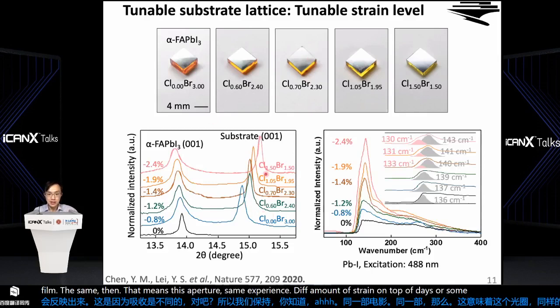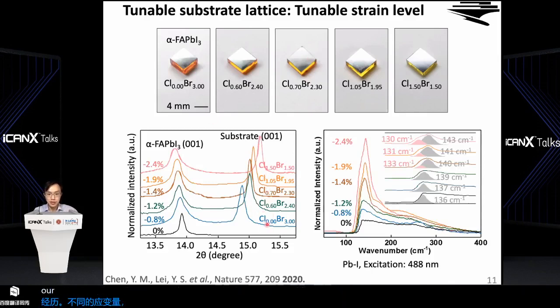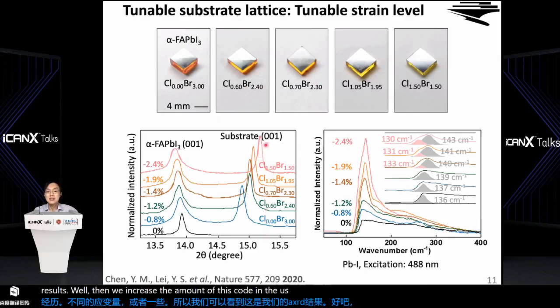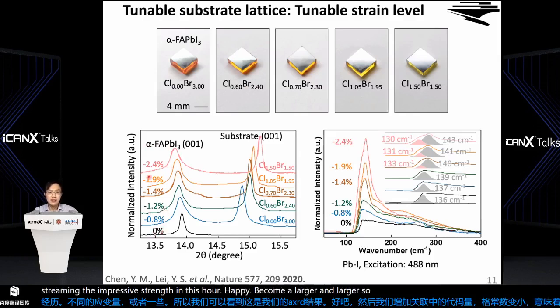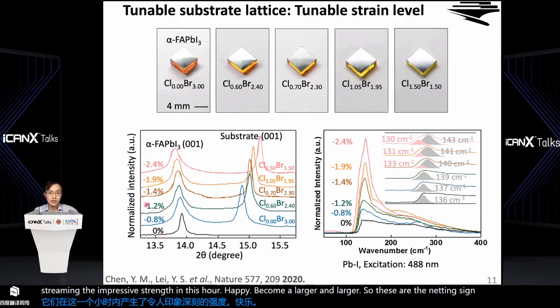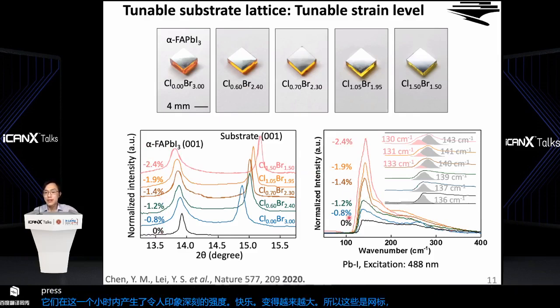So you can see this is our XRD result. When we increase the amount of chlorine in these substrates, the lattice constant becomes smaller and smaller. Then that means the compressive strain in this alpha FAPI becomes larger and larger. So this negative sign denotes compressive strain in this case. And this compressive strain is also reflected by the Raman spectroscopy we can collect.